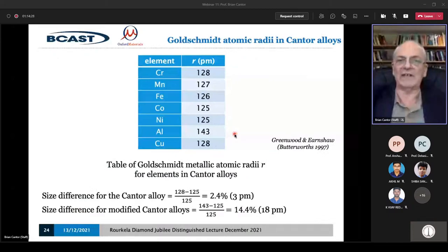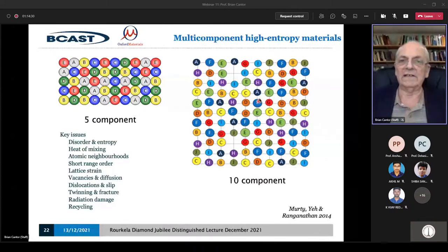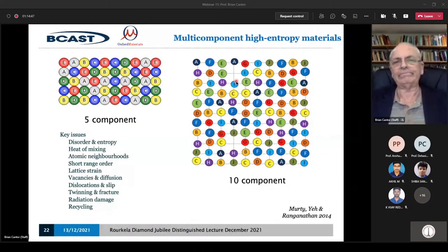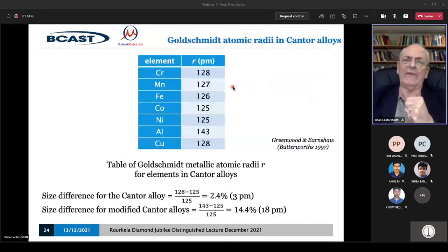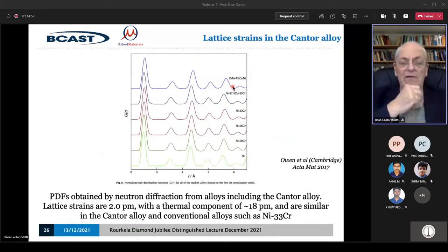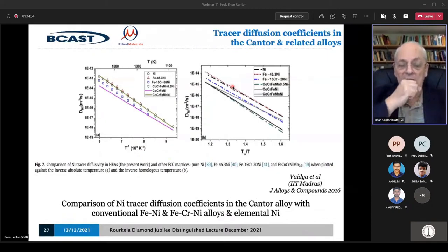And if there's a vacancy, an adjacent atom can jump into the vacancy, or the vacancy, you can say, can jump to here. It's really the atom jumping into the vacancy. But that can then happen again. And as the vacancy moves around, the atoms are moving around. So atoms move around in a material at high temperature because of this vacancy hopping. But when you have a material where every atom is copper, or every molecule is silicon oxide, the vacancy hopping takes place at a certain rate, but it goes through a consistent material.